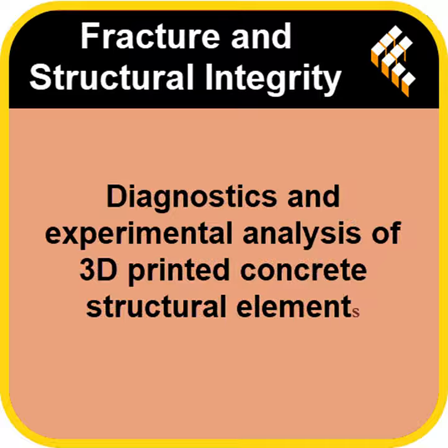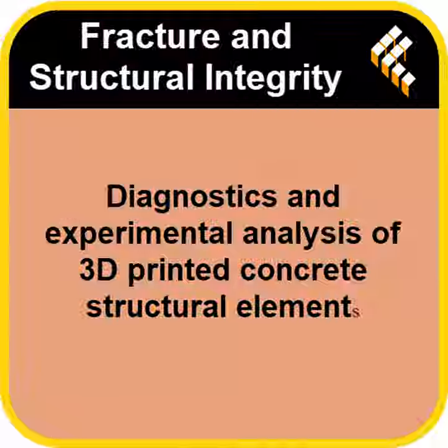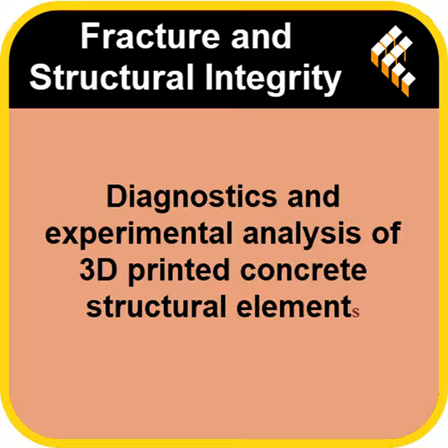And what about water absorption? That tells you how porous it is. Exactly. An inverse trend there. The specimens that had visible layer separation had a huge jump in porosity. Water absorption went from about 5 or 6% up to nearly 9%. So more porous means weaker. And they calculated a strong inverse dependency there, a correlation of negative 0.76. It's a clear flag. If the material is soaking up too much water, it's almost certainly weaker at the interfaces.